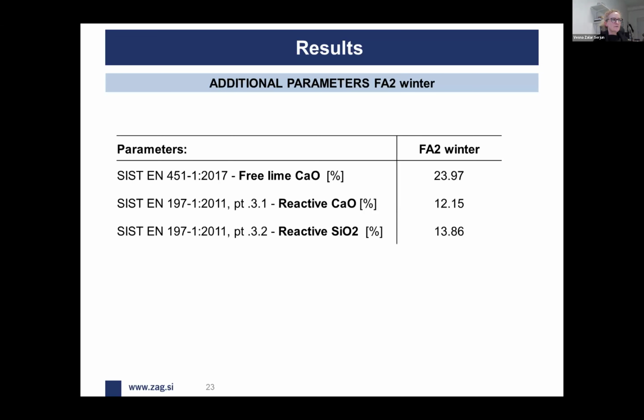We can see that the free lime content, according to the standard parameters, is quite high. It's too high than prescribed for usage in cementitious composites, and it includes also quite a high quantity of reactive calcium oxide, which on the other hand is very promising also for the carbonation processes.